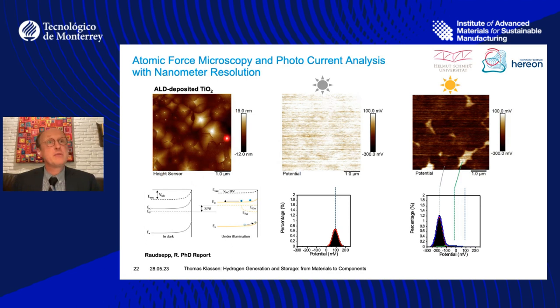That's the usual imaging mode, and it tells you how rough your surface is. But we can do something more. We can also let a current run through the AFM tip and see where we generate electrons at the surface, charges at the surface, and where our active centers are. So here you see this is in dark mode.